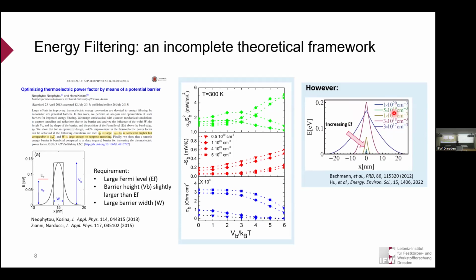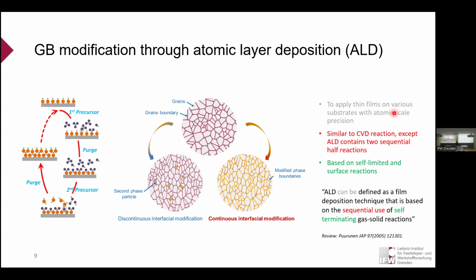So is there any possibility that we can mitigate this contradiction? So we come up with the idea that we can still choose a material that has a high Fermi level, which basically means a heavily doped semiconductor or even a metallic material. And then we can extrinsically increase the barrier height by adding, for example, a resistive barrier, even oxides. So with this idea, we use this technology called atomic layer deposition to coat the grain boundaries.